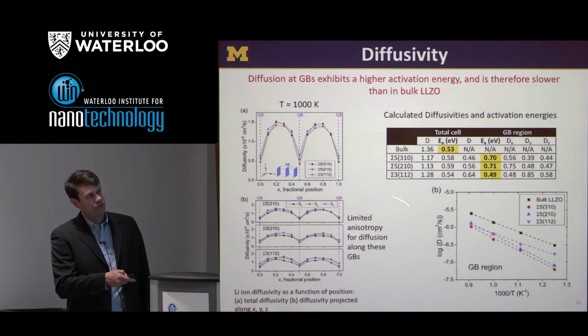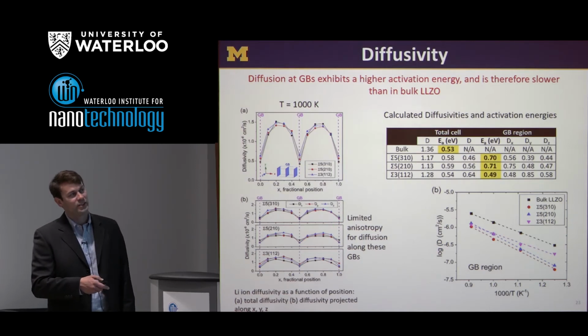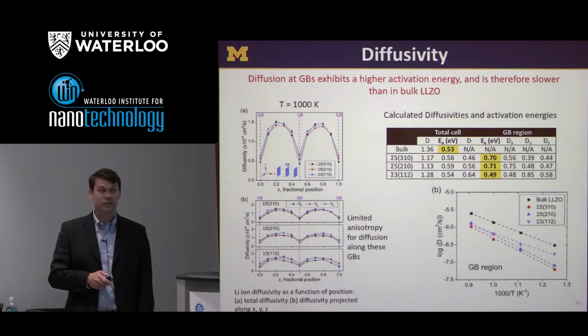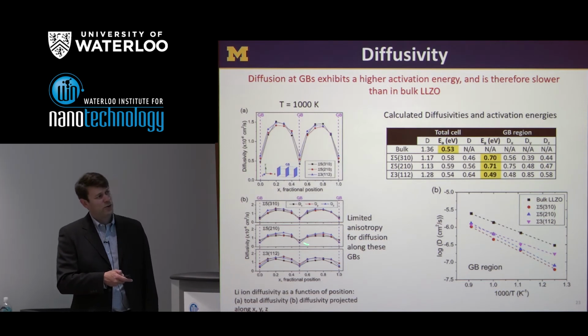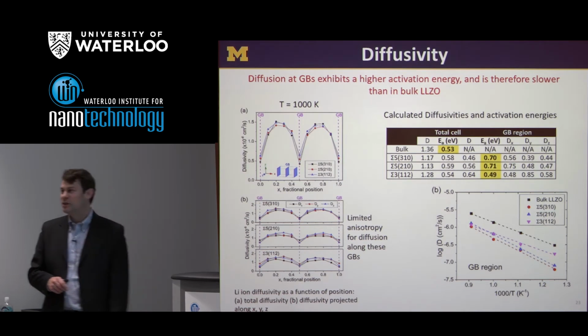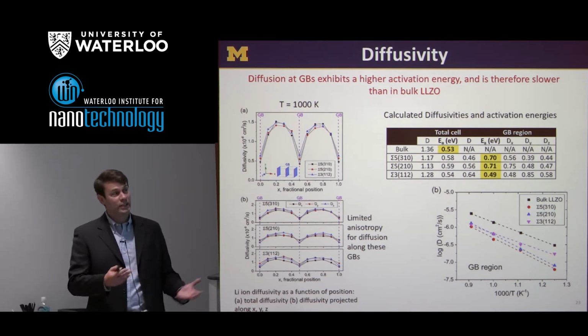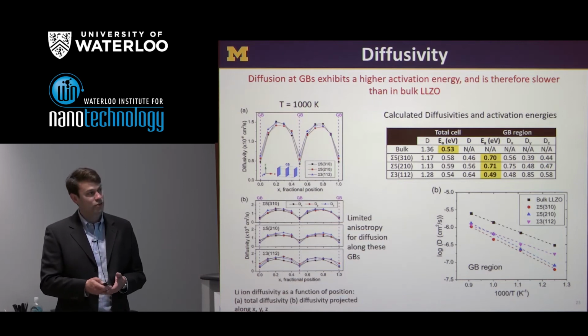We can also look for anisotropy by projecting these diffusivities. I don't know if you can see these colors, but the different colors represent diffusion in either of the 3 Cartesian axes. And so an anisotropic grain boundary would have a big spread in the diffusivities in the boundary plane, and we don't really see much of that effect here, which suggests that at least for these boundaries, there's limited anisotropy for diffusion.